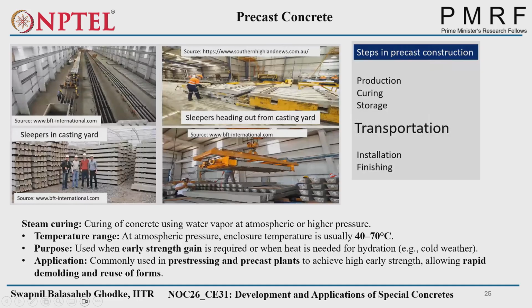But in precast construction, the curing is mainly done by steam curing. Steam curing means curing of concrete using water vapor at atmospheric or higher pressure. The temperature range is between 40 to 70 degrees at atmospheric pressure. The purpose is early strength gain, because as we are producing in the warehouse, a continuous production process is needed. So we have to create early strength gain to remove the formwork as early as possible. Steam curing is applied in prestressing and precast plants to achieve high early strength, allowing rapid demolding and reuse of formwork.